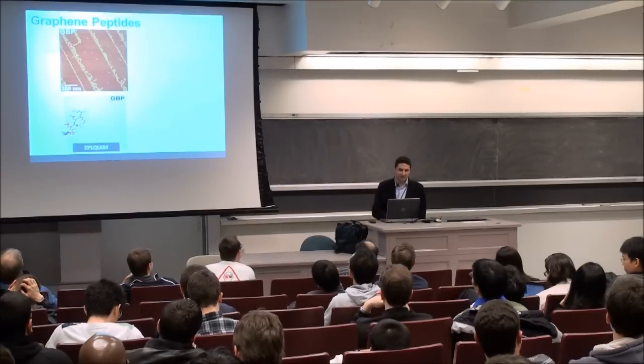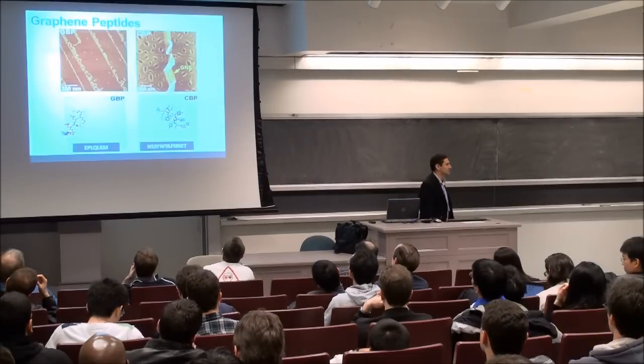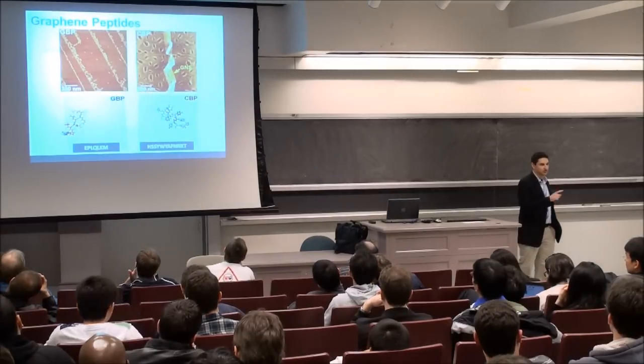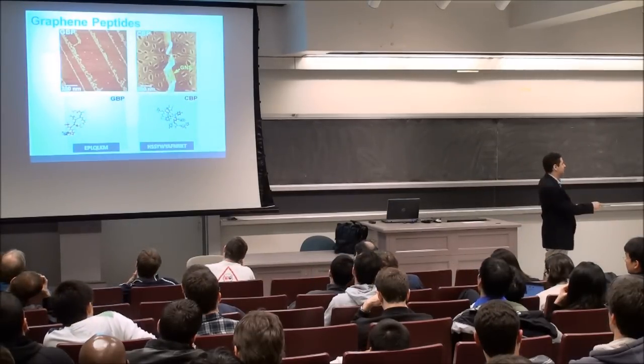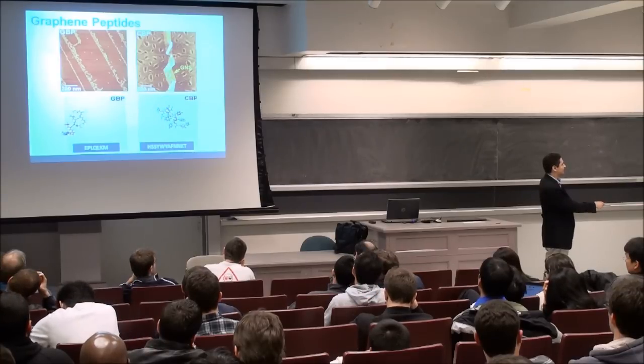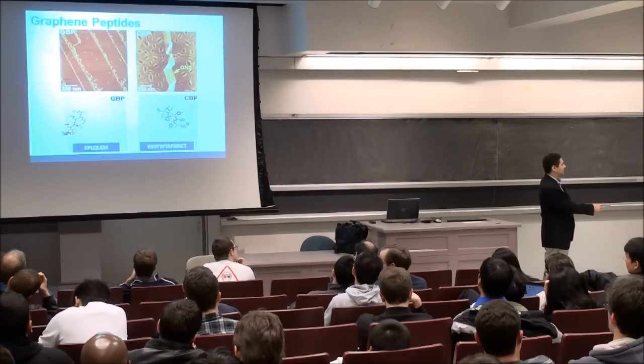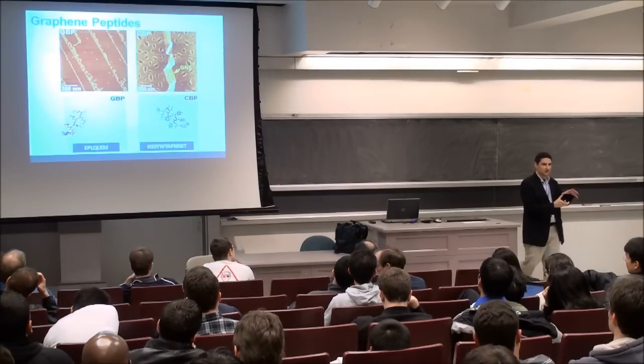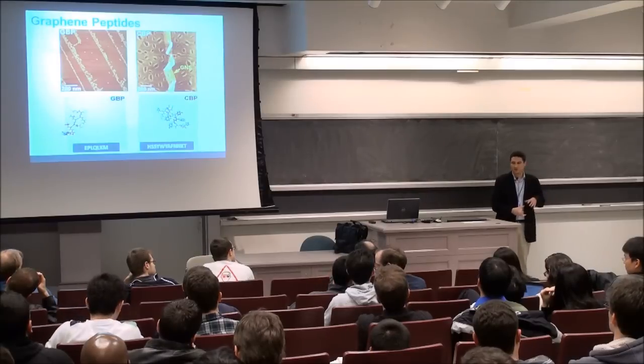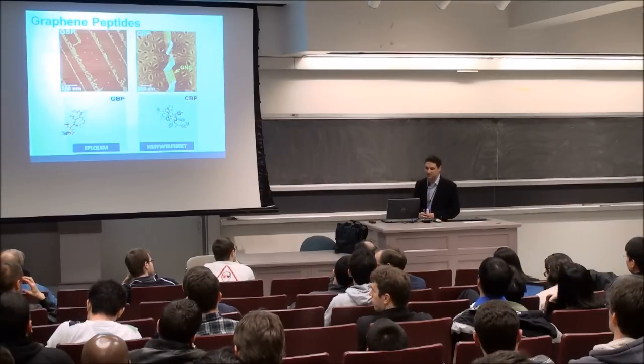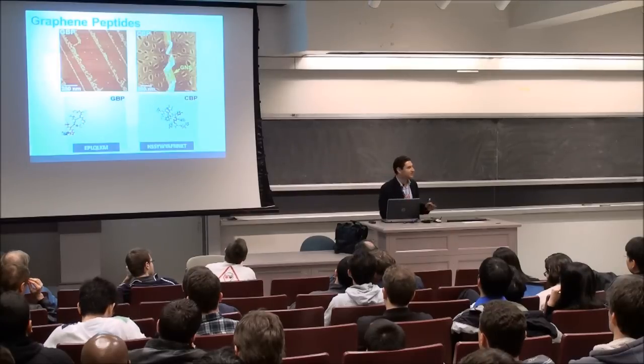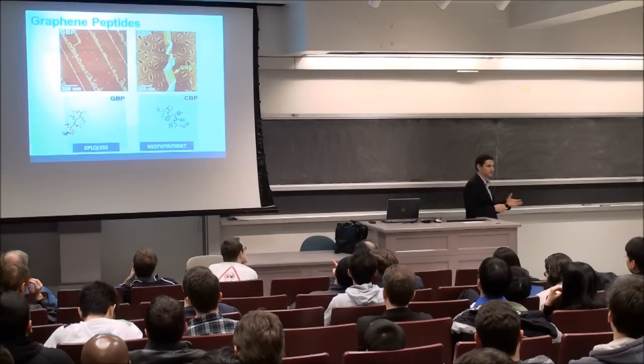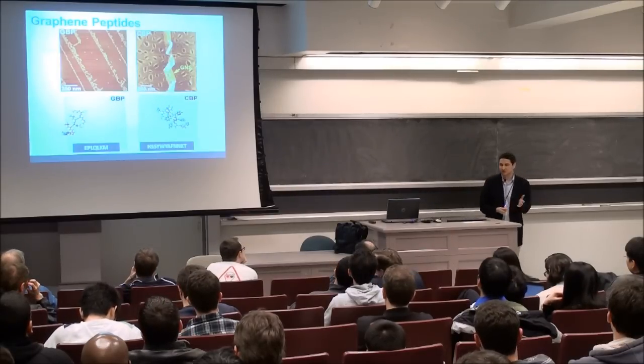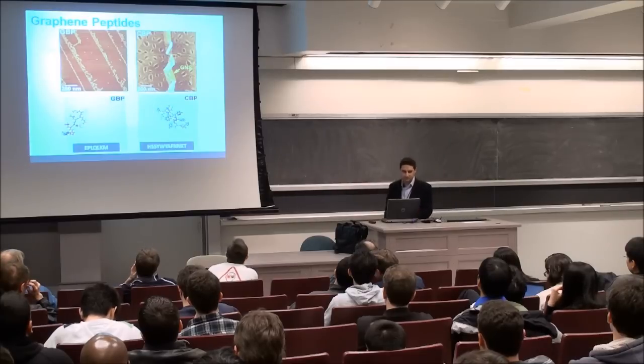You can also generate peptides in this process that actually cover the entire sheet of the graphene. So these are planar binding peptides here that cover the entire graphene sheet there. We can do modeling that show that because it has a lot of aromatic rings, they actually pi stack with the graphene, they'll actually laminate across the entire sheet of the graphene. So these peptides actually do different things. They can either bind to the edges or to planes based on their chemistry, which was pretty cool.